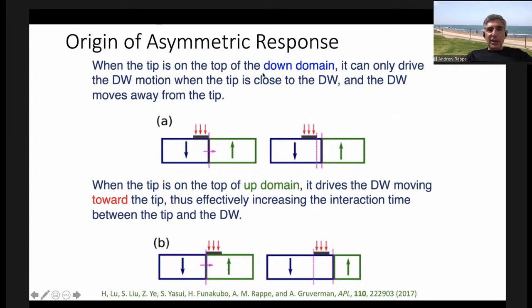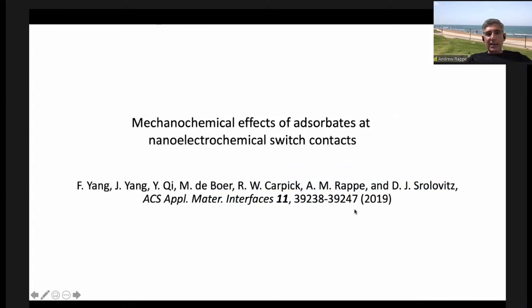So when the tip is on top of the down domain, it can only drive the domain wall motion when the tip is very close to the domain wall and the domain wall moves away from the tip. When the tip is on top of the up domain, it drives the domain wall moving toward the tip, thus effectively increasing the interaction time between the tip and the domain wall. And so this is the citation for that paper here.